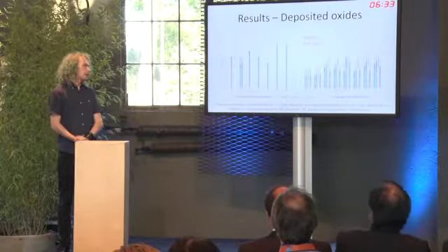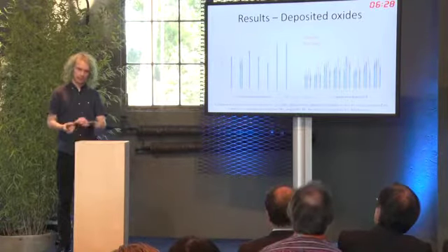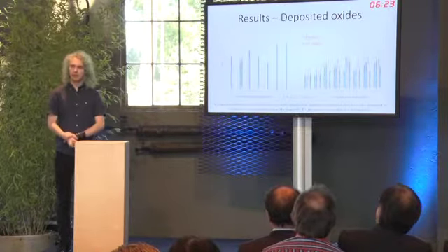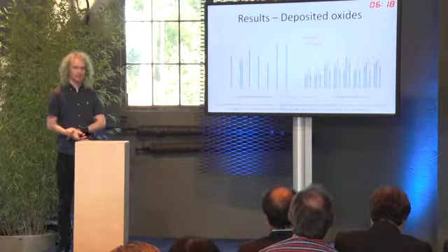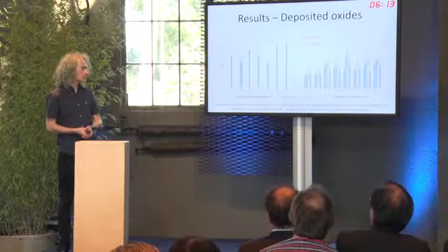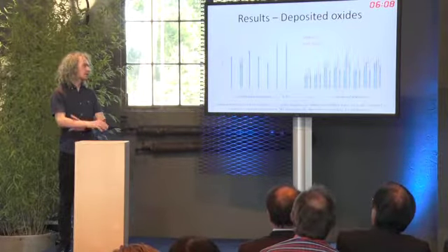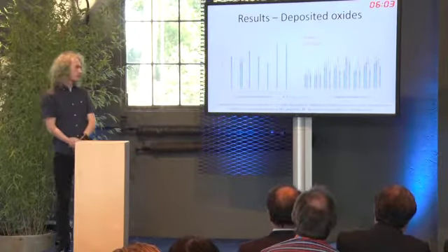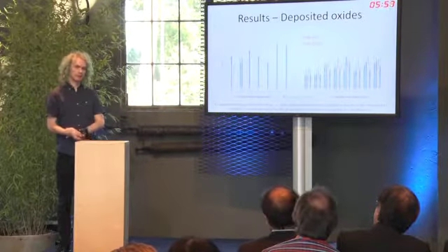However, what we found is that the contact itself between the ball and the plate actually seemed to be plowing through the oxide, and so it seems that this mechanism was the one which was causing such a high increase of friction. The thinner magnetite layer, for instance here, which was substantially thinner than the others, actually has a reduced coefficient of friction, probably because of this. It is a bit problematic actually trying to use this method to study these oxides.